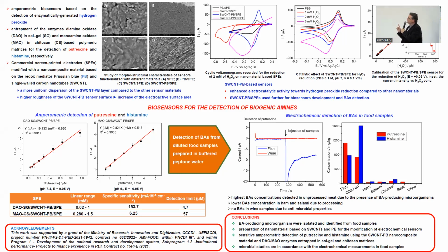The results obtained in the electrochemical measurements were correlated with those obtained in the biological studies. Thus, it was observed that the highest concentrations of histamine and putrescine were detected in the spoiled meat samples, as well as the fish ones, where a variety of biogenic amine producing microorganisms were identified. While for wine samples, for example, no biogenic amines were detected due to their antimicrobial properties.